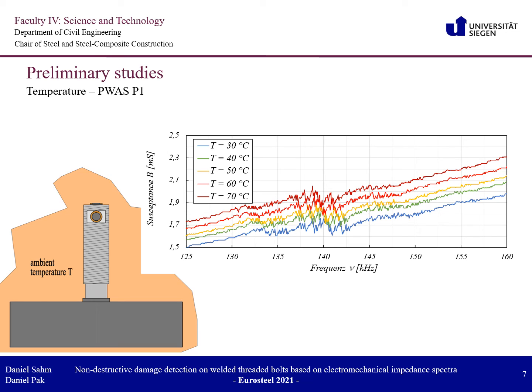It can be seen that the amplitudes of the spectrum do not seem to change. Rather, it can be observed that the temperature increase causes a shift of spectra into higher susceptance range with simultaneous slight rotation. The rotation of the spectra can be recognized by the fact that the vertical distance between the spectra also increases with increasing frequency. This is a plausible development since an increasing temperature results in a reduction of the steel's Young's modulus and thus the modes shift to lower frequency range.